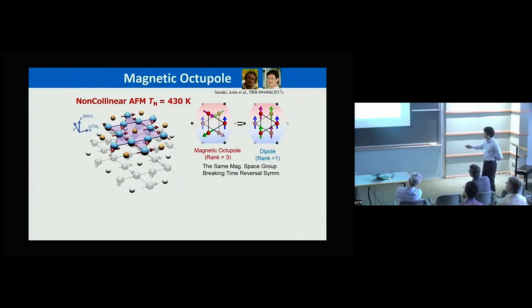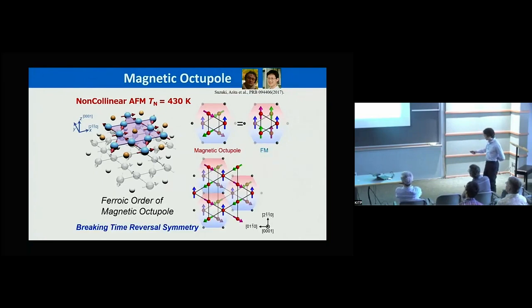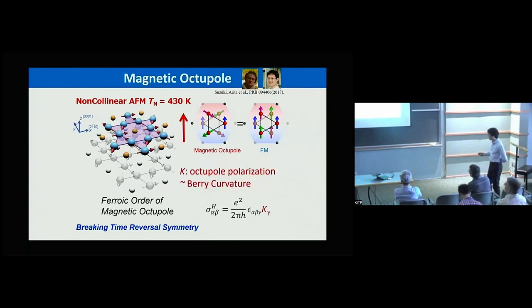And you can actually see this magnetic texture as a Q equals 0, or a ferroic order of magnetic octupole. So this breaks the time reversal symmetry macroscopically, and that's the reason why you see the anomalous Hall effect. If you like, you can take this octupole polarization as an order parameter of this observed anomalous Hall effect, and maybe it can be a linear relationship. Okay, and this is a kind of working principle, working hypothesis. Okay, then let's go to the strain control.